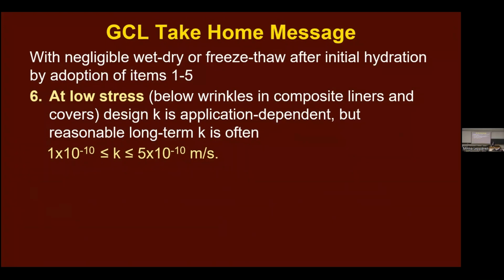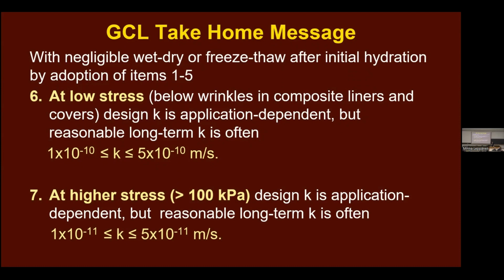With negligible wet, dry and freeze-thaw cycles after initial hydration, so if you do the first 5 things I mentioned, at low stress, your hydraulic conductivity needs to be considered in its particular context, but more often than not, it's going to be between 1 and 5 times 10 to the minus 10. Based on over 30 years experience of doing this, that's where typically it sits at low stress. At higher stresses, it's typically in the 10 to the minus 11 to 5 times 10 to the minus 11 range.